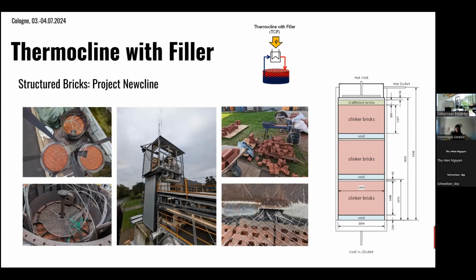We had some ideas here, so we did some wire mesh between the layers of the bricks. So in case there is some blocking of some channels in the flow, the bricks are separated on each layer. So there can also be some redistribution of the flow. And then we had a company who was cutting all the bricks and fitting them in the baskets. Obviously, if you go to a larger scale, you would want to have much bigger of these bricks, but in this project we were focusing on something readily available.